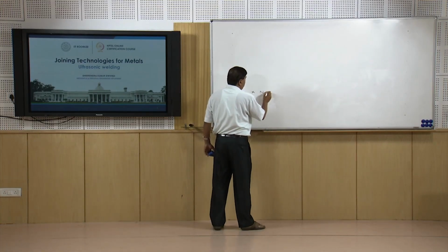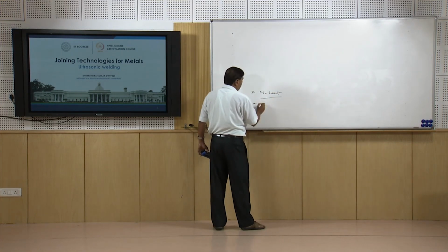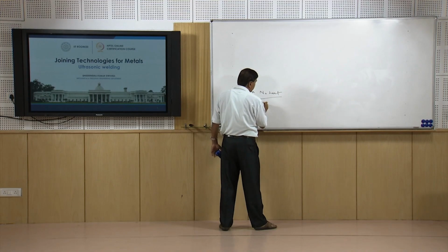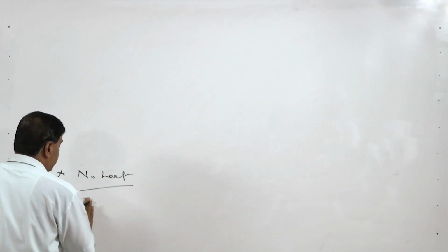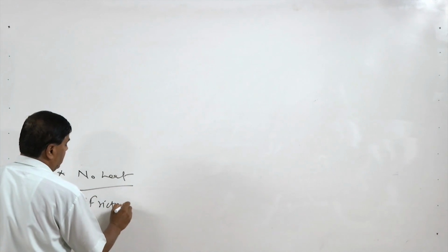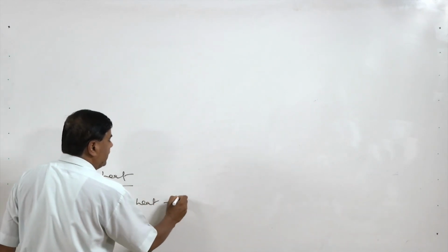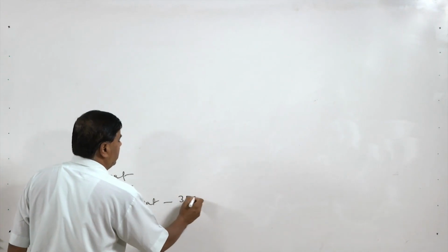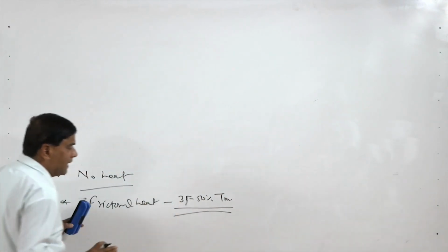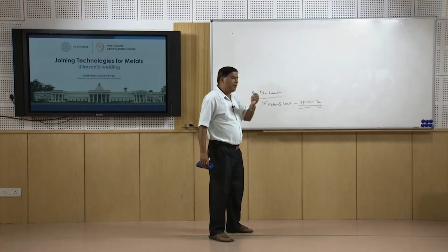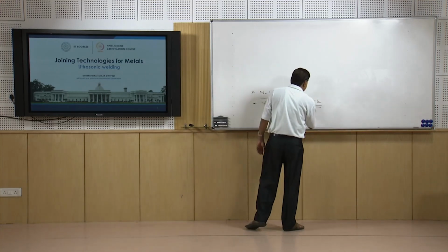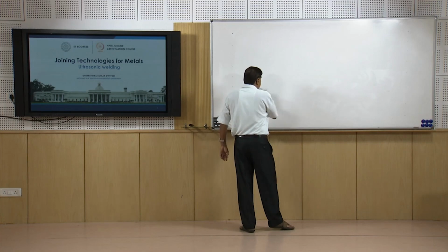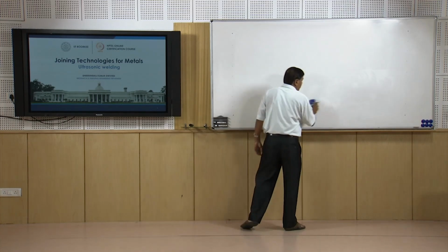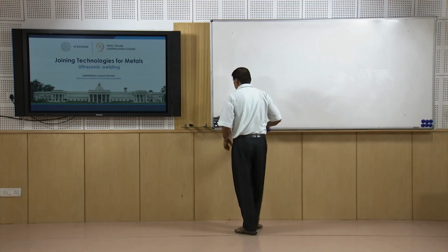So, keeping this principle in mind, we see that no external heat was supplied. We did not supply heat from the outside, and despite this, only the frictional heat caused enough temperature rise, like say 35 to 50% of the melting point of the metal in Kelvin scale, which is found to be enough for recrystallization of the material, and the plastic deformation coupled with the recrystallization results in the refinement of the grain structure also.